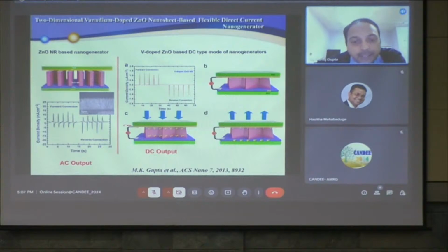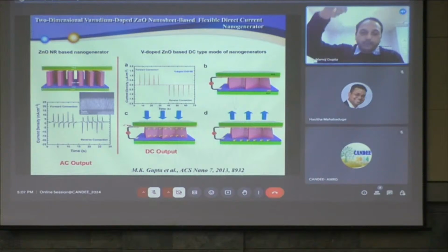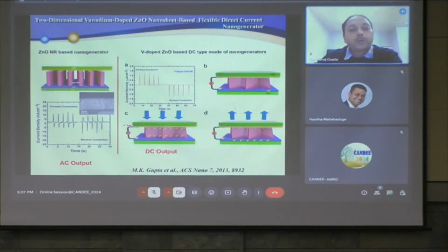Now when we apply the mechanical pressure, you see the negative and positive voltage was created here, right? And this positive pulse we got. Once we release the pressure, like we have a computer-controlled force simulator where we can apply the force at a controlled frequency, at a controlled Newton, and then we record the output voltage or output current from our electrometer. Now you see the current was almost 1 microampere per centimeter square, which is very high.